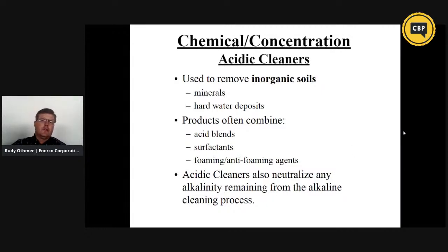Our good passivation layer on our stainless is preserved by keeping it slightly acidic. And it's in addition to its ease of cleaning and so on and so forth. Stainless is chosen in the brewery industry because our beers are largely acidic and they play very, very well together with the stainless.